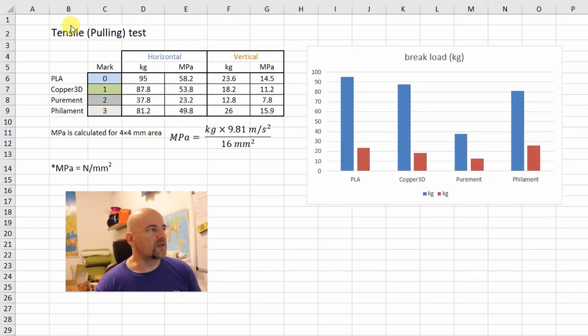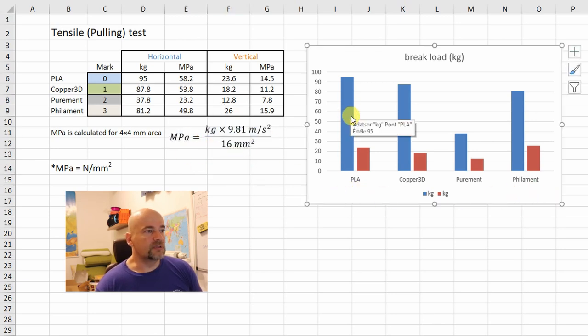Okay, in this table you can see the results of the tensile or pulling test. These values are in kilograms measured with the horizontal test probe, and these are values with the vertically printed test probe, which are of course smaller. I also calculated here in megapascals or newton per square millimeter. Here you can see the equation of the calculation, but let's see the graph. So it looks like they're quite similar except the Purement.